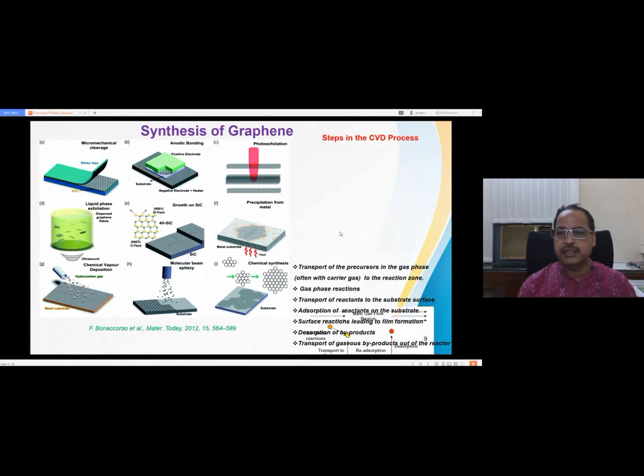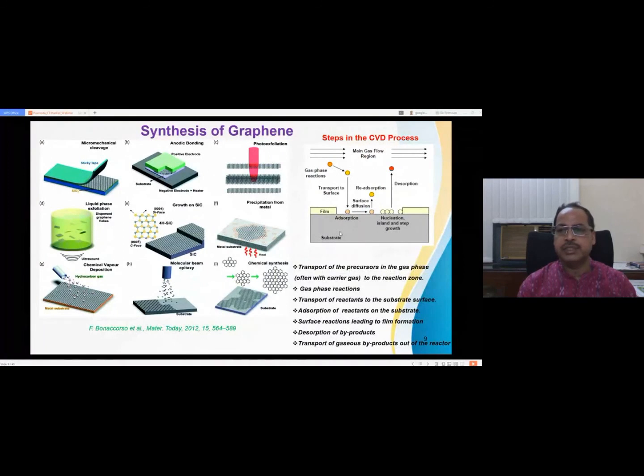So what will happen? This is the schematic of the CVD process. First there will be the gas phase reaction, then the transfer to the surface, because we have some carrier gas. Then the chemical reaction will happen and it will adsorb on the surface, and there will be some surface diffusion. Then there is a reabsorption, and you will find some nucleation sites and islands will grow, and then desorption of the byproduct, and you can get the film.